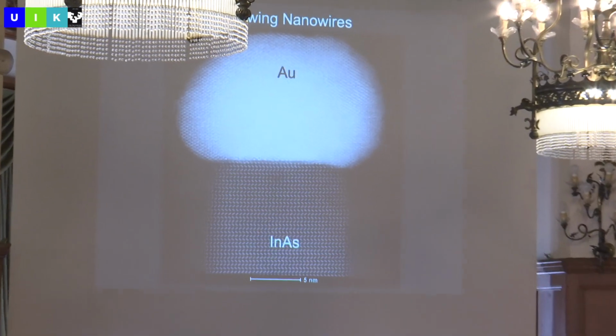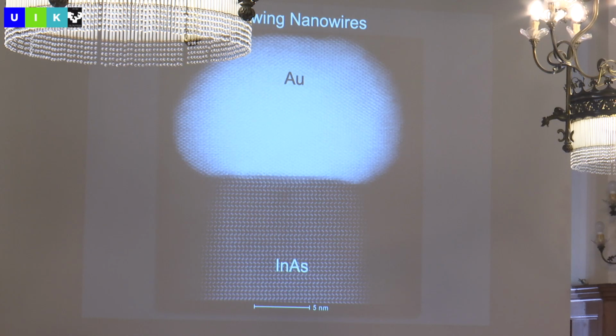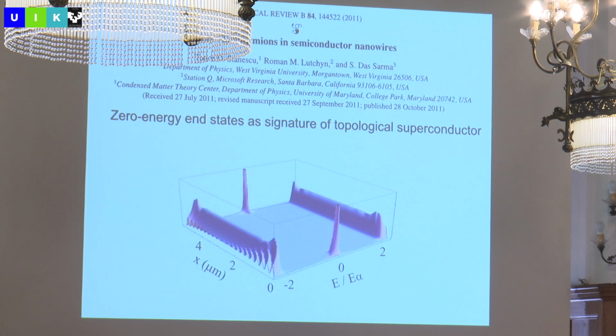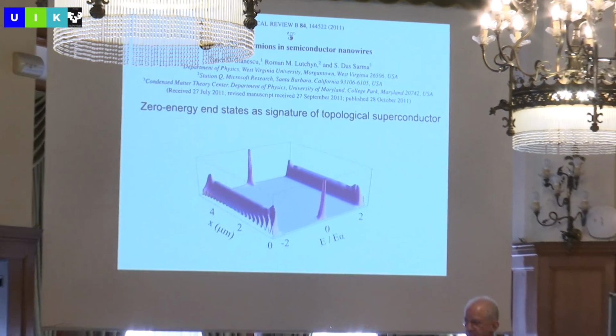You can even see in this electron micrograph. This is a remarkable micrograph. This is the indium arsenide crystal rising up from this growing gold ball that just then gets pushed up into the air as the crystal grows underneath it, growing the nanowire, leaving behind this atomically precise, more or less, with some defects that are important, one-dimensional wire that grows underneath the gold ball catalyst. So that would give a wire. And then you can do the rest of the ingredients that those two papers from Oreg and co-workers and Lutchyn and co-workers told us to put together.